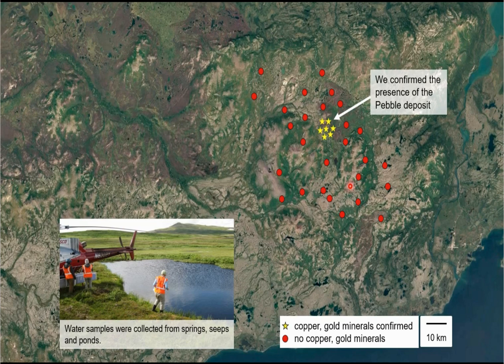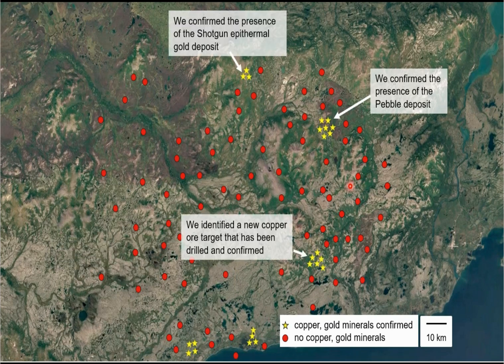sulfide in the subsurface. We then moved out and we were able to identify another already known epithermal copper gold deposit up here. And then using only the water compositions, we were able to identify 1, 2, 3 new targets, where this target, we could use the metal isotopic composition of water to predict what copper sulfide should be in the subsurface that the water reacted with. And the copper sulfides we predicted should be there, they've been pulled up by drill core.